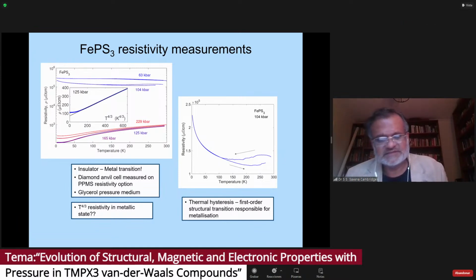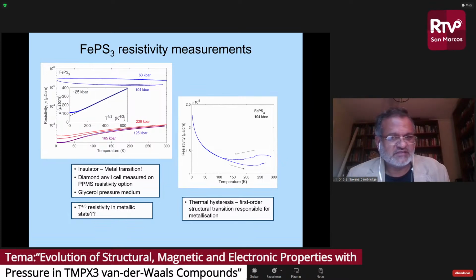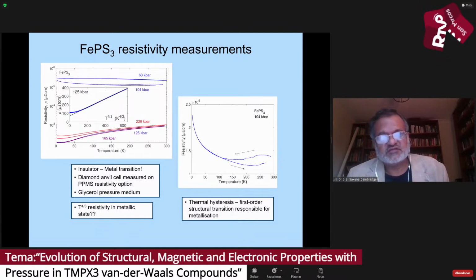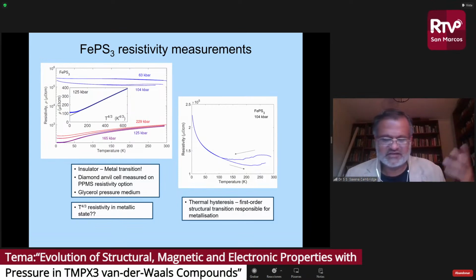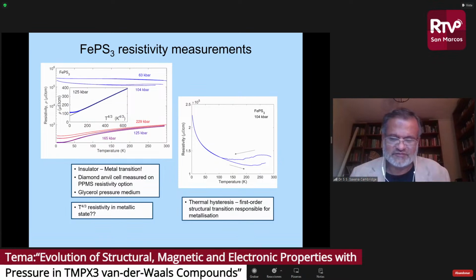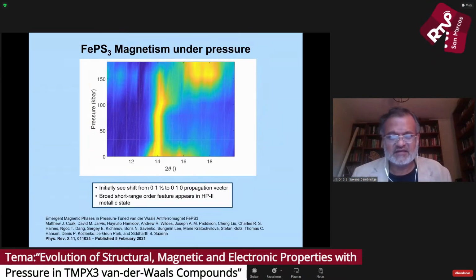Then we're also doing X-ray synchrotron work for the structural side to map onto the electronic properties. But how the magnetic properties are directly evolving is obviously very difficult to determine in a lab-based experiment at these pressures, not because of the pressures so much, but because the moments are pretty small and the samples are pretty small. So magnetometry of the normal kind gives you lots of features and you cannot be sure which one is true or not. So the one real robust tool, of course, is neutron scattering.